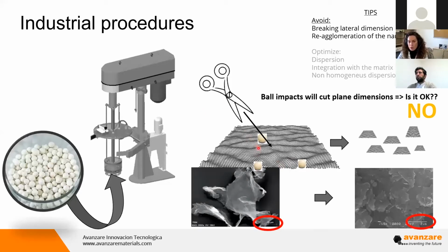Because, for example, if we put this in a dispersion mediated by balls, these high impacts are going to break and damage this plane and will cut it. So what we have at the end is not this initial dimension, but a smaller one. So for the percolation, we will require a much higher dose than expected. So it's necessary to avoid breaking the lateral dimension.